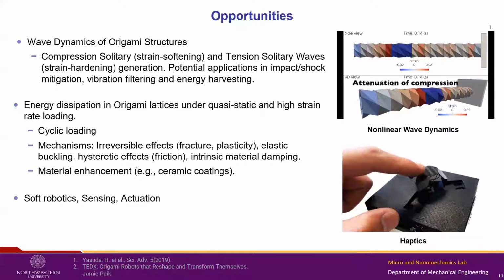We also feel that these origami lattices can have some interesting energy dissipation properties from cyclic loading, elastic buckling, hysteretic effects from friction, etc. And we can also do some material enhancement, because here we just showed origami structures printed with a single material, a common photolithography material, but we can improve the properties that we want, for instance, with ceramic coatings or even metallic origami. And then, on the side of applications, not so much the fundamental aspects, they can be applied for soft robotics, sensing, actuation, and pretty much everywhere we need tunable properties, where we can change them based on the level of actuation, and where we can also leverage the foldability of these origami structures.